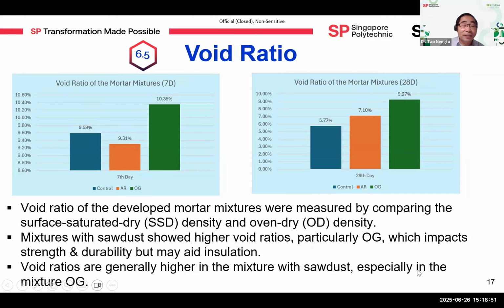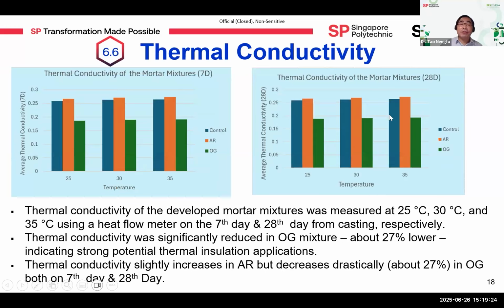Void ratio of the developed mortar mixtures was also measured by comparing the surface saturated dry density and oven dry density. Mixtures with sawdust showed higher void ratios, particularly OG, which impacts strength and durability but may help insulation. Void ratios are generally higher in the mixtures with sawdust, especially in the mixture OG. These two photos show the void ratio of the mortar mixtures at 7 days and 28 days respectively.